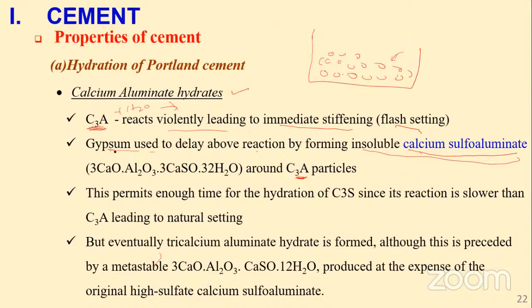So if this reaction was to occur very fast, and our paste hardens quickly, then we might not be able to get the strength that we require. And remember, we say tricalcium aluminate is not responsible for much of the strength. So to delay this material from reacting fast, the gypsum comes in place. It coats the particles so that tricalcium aluminate is covered by this insoluble calcium sulfoaluminate. This gives enough time for tricalcium silicate, which is the one that gives much of the strength, to react and gain strength, leading to normal setting.